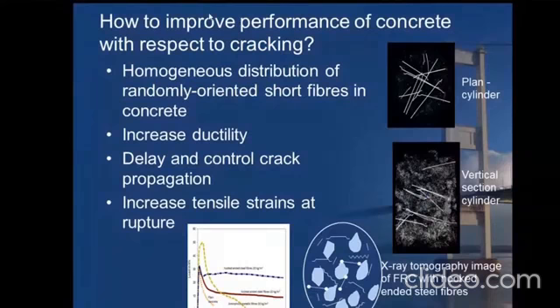So what happens is, with high strength concrete, when you want to increase its ductility, fiber should be incorporated in order to overcome that disadvantage. As I told you, after diagnosing the advantages and disadvantages, the material scientist should be able to appropriately rectify the disadvantage by using the correct material. So when I'm going for high strength concrete, where ductility is a major problem, high strength concrete can be converted into a fiber reinforced high strength concrete, where steel fibers can be added in the matrix and the ductility of the structure can be improved.